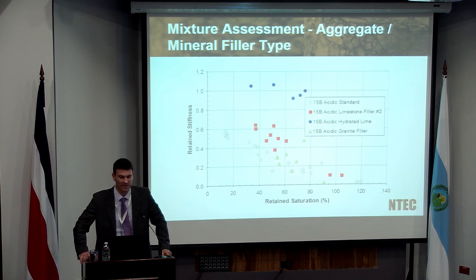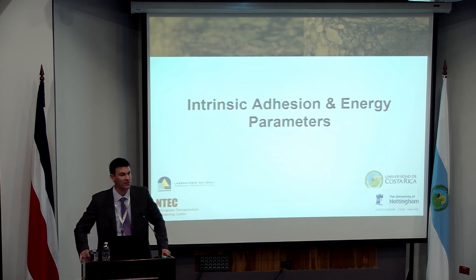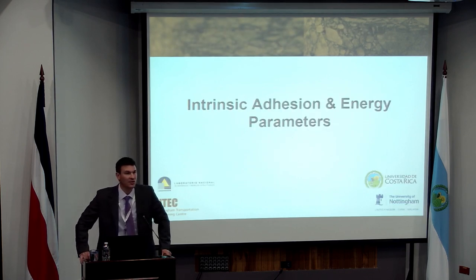And so what we were trying to do in this study was take that data, some of it from the field, some of it from the lab, and now try to understand what is exactly the driving mechanism. And we did this by looking at three stages. The first stage is looking at the fundamental intrinsic adhesion or surface energy characteristics of our materials. So this is work that we started about 12, 13 years ago, using some of the concepts that were developed initially at Texas A&M University. So they were looking at about the same time at a very similar approach in terms of using surface energy to measure some form of indirect bonding, if you like, between the bitumen and the stone.